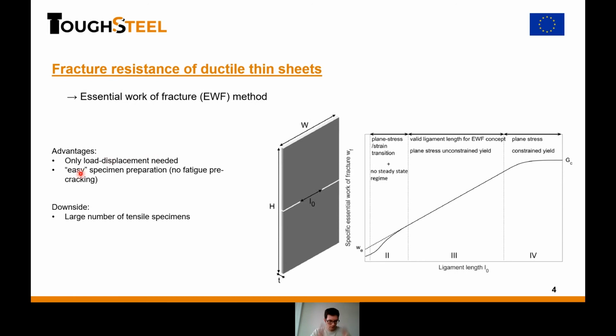The second one is an easy specimen preparation, because you do not need fatigue pre-cracking. But like David said, it's not as easy as that. You need the notch radius to be small enough, but this is material dependent, and luckily for me, for all my materials, I did not need to do fatigue pre-cracking.